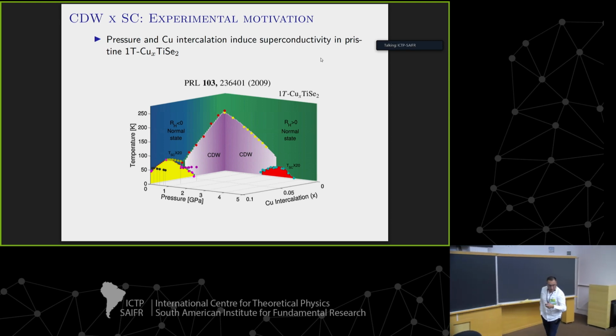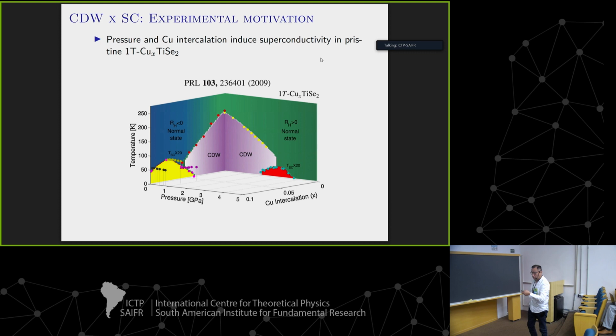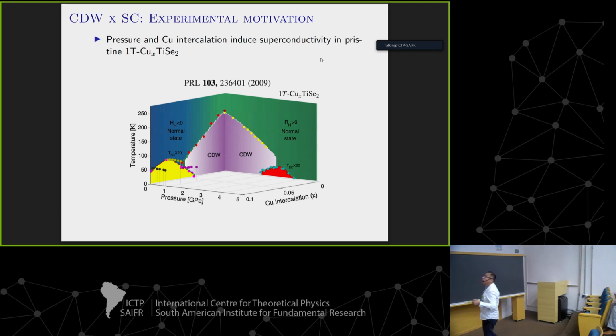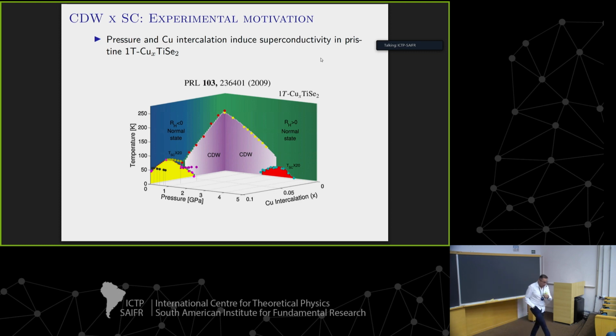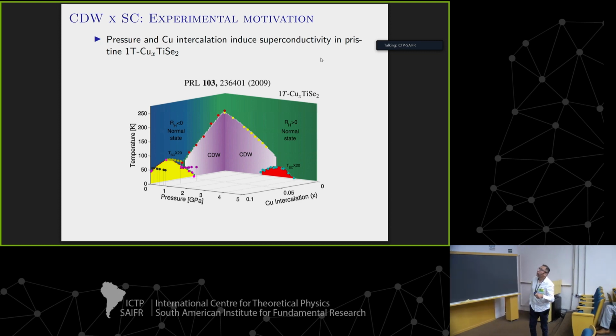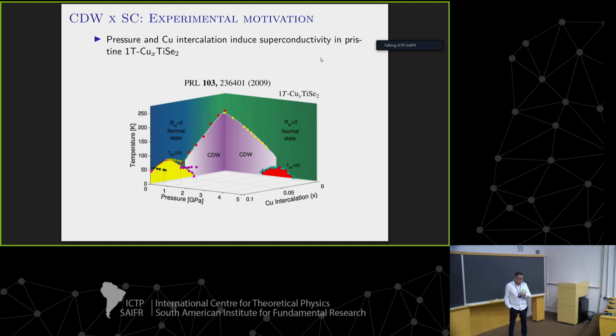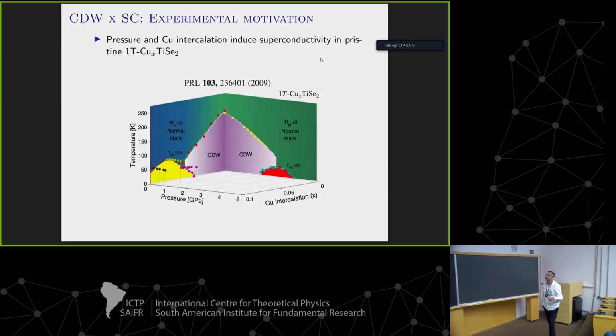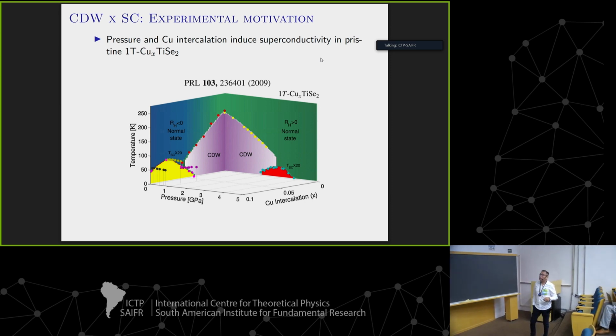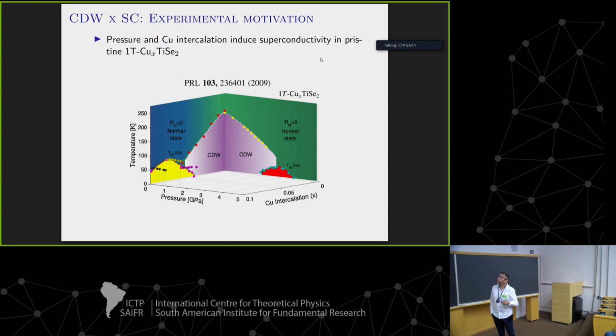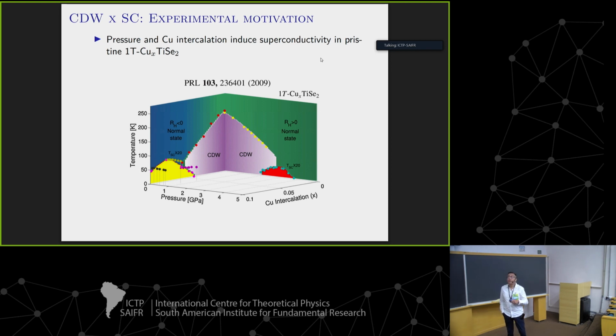Now here I show this very well-known experimental result. This is a very well-known TMD compound, copper-doped titanium diselenide, and we can see from this experimental phase diagram, temperature as a function of pressure and copper intercalation, the different phases, for instance, the charge density wave here, and this is the superconducting dome.